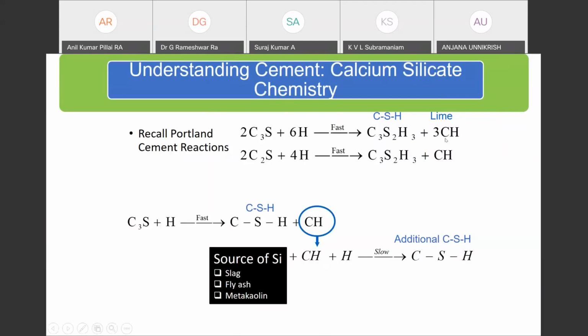It also gives off a lot of CH, which is calcium hydroxide, which makes concrete very alkaline. So basically, concretes are very, very alkaline. They produce a lot of calcium hydroxide. And the calcium hydroxide doesn't contribute to strength. It's just a byproduct of the reaction. So one of the earliest attempts to reduce the clinker, which is what gives us these calcium silicates, was to look at this calcium hydroxide, which is sitting idle in the system, and utilize it by dosing additional forms of silica. And as luck would have it, we found additional forms of silica from waste materials.